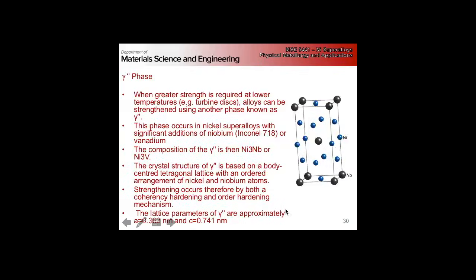And it's a DO22 crystal structure - it's body-centered tetragonal rather than FCC, so it's not as coherent. So we have a coherency hardening effect and an order hardening effect, and our lattice parameters we don't have quite the same match.